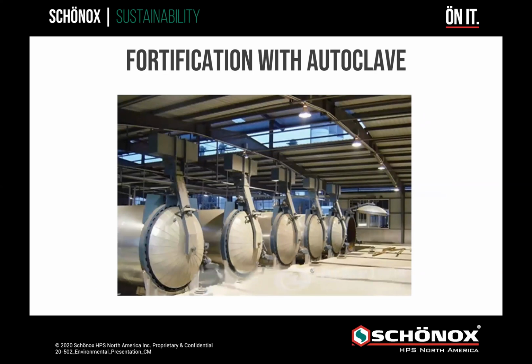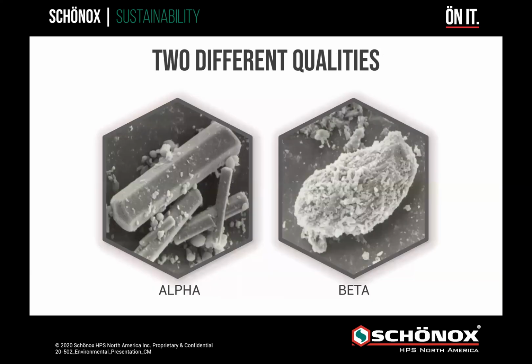You're looking at an autoclave that we use in order to fortify that material. If we keep that calcium sulfate slurry under high pressure and high heat, it will become an alpha particle system, which gives you high strength, high durability, and high flexural strength that we could not get with a natural gypsum. If you look at it under a microscope, keeping it in that autoclave will give you that alpha particle, that hexagon shaped material. If you look at the Schönox logo on the bottom of your screen, you see the little S in green. That is there as a representation of the hybrid synthetic gypsum alpha particle.